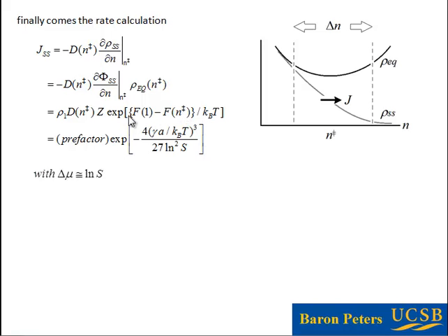Note the structure of this formula. This is literally giving you the population of critical nuclei. I've got the mobility factor here. Zeldovich is converting between this kind of derivative and the equilibrium probability. If I take rho 1 and multiply by this exponential, remember that this exponential of Fn minus F1 is the ratio of nuclei of size n double dagger to nuclei of size 1. Then I multiply by nuclei of size 1, and what do I have left? I have the population of critical nuclei.